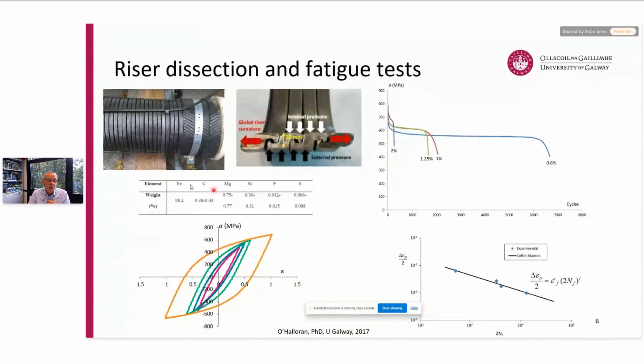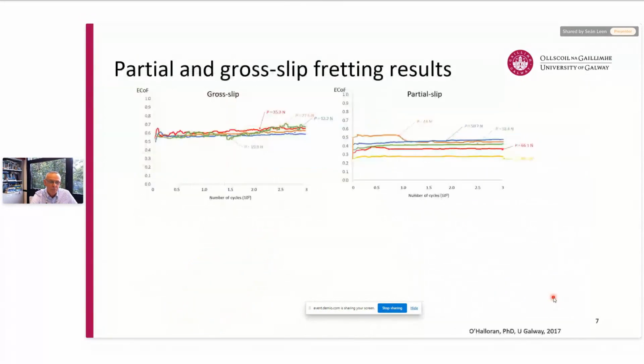And then here's some characterization of the composition of the material. And then really I'm showing here some strain control fatigue test results in the bottom left. These are the stabilized loops for different low cycle fatigue strain control tests. And then you can see here the stress evolution in those tests ultimately leading to failure. And then you can see in the bottom right the typical Coffin-Manson type strain life, plastic strain versus life data that we obtain from that, and the kind of fits that we use to help us in our modeling.